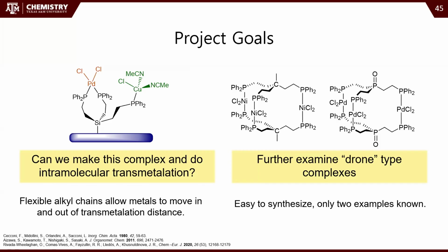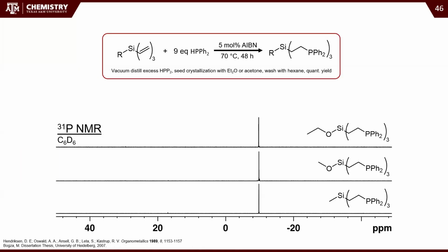This is it. So we thought, okay, well, we're already going to be making a new ligand, and might as well see if we can get a couple of these as well. So we're going to start with the solution chemistry for drones. Making the ligands is pretty straightforward. We just start with the trivinyl silane, and then add in a bunch of diphenylphosphine and do radical initiated hydrophosphination. And then we can just vacuum distill off all of the excess diphenylphosphine, and we're left with the really viscous, thick oil.